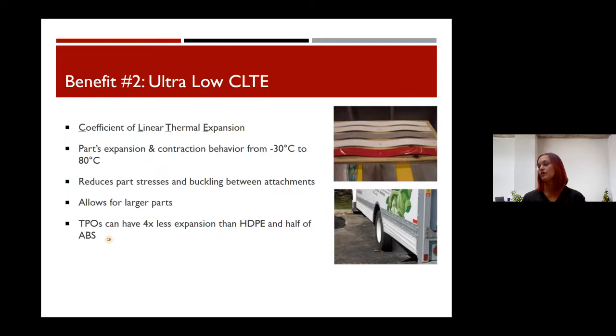Parts that have a long span, like you can see in the photo there, those bottom skirts for the U-Haul were moved to TPO because of what's happening in that top picture. They're warping in between the connection points. There's a ton of rivets down the side of that thing, and basically there's no room for the expansion and contraction of an HDPE. And so it's got to go somewhere, and it makes this bacon shape. So overall, TPO has 4 times less expansion than the high density polyethylene. So we see that a lot in flat panels or big kind of shoebox lid shapes.